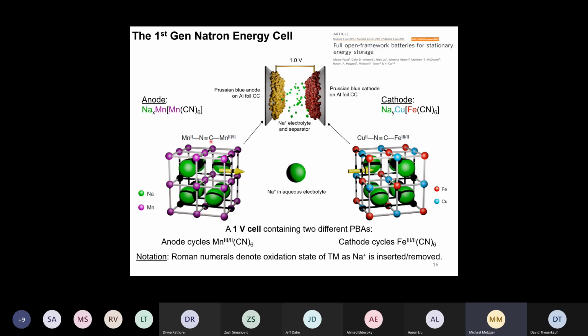So you can see here, we start off with manganese atoms on the corners of these little cubes. And the way Natron likes to write the structure is in this way, which is also quite useful. So we have manganese 2+ ions. That's these ions here, or atoms, which are coordinated to nitrogen. And then we have the CN bond, and the manganese, which is coordinated to the carbon, would be this one in our way of writing it. And in their cell, this one changes the oxidation state between 2+ and 3+ as we sodiate and desodiate this material. So as we remove the green balls.